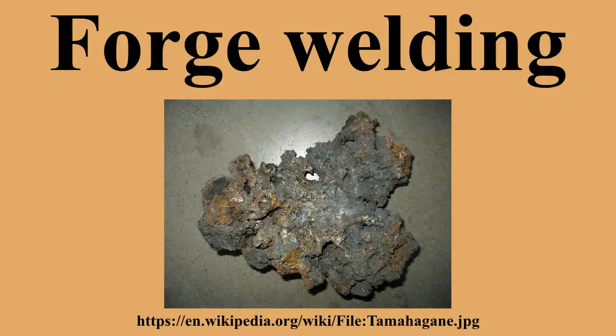Decarburization. When steel is heated to an austenizing temperature, the carbon begins to diffuse through the iron. The higher the temperature, the greater the rate of diffusion. At such high temperatures, carbon readily combines with oxygen to form carbon dioxide, so the carbon can easily diffuse out of the steel and into the surrounding air.